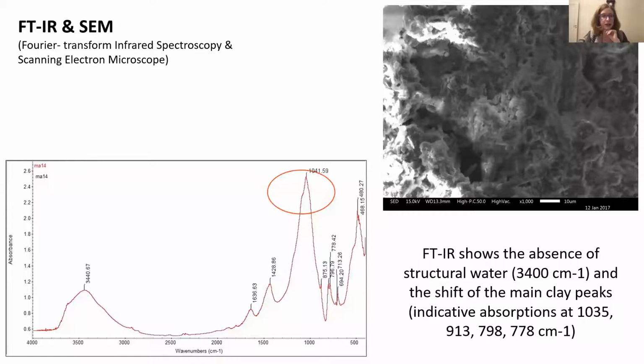And in this case, this is quite visible in the FTIR, which shows the absence of structural water and the shift of the main clay peaks that actually occur during a conflagration event. You can also see the initial signs of vitrification in the SEM photo.